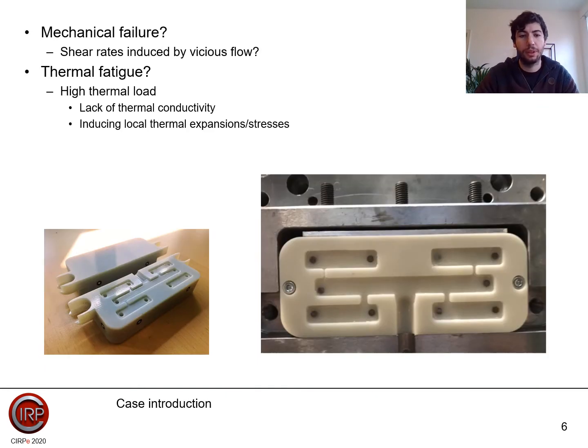In previous work, we already hypothesized that the shear rates induced by the plastic melt that is being injected are the key factor determining the failure of the plastic additive manufactured insert. This hypothesis was based on the observation that the mold consistently failed at locations where the highest shear rate occurred during the injection molding process.